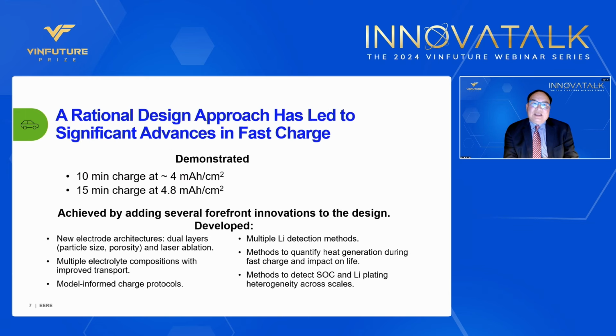You can see that a rational design approach has led to significant advances in fast charge. By applying those processes I described on the previous slide, we have demonstrated a 10-minute charge at 4 milliamp hour per centimeter square, and a 15-minute charge at 4.8 milliamp hour per centimeter square.